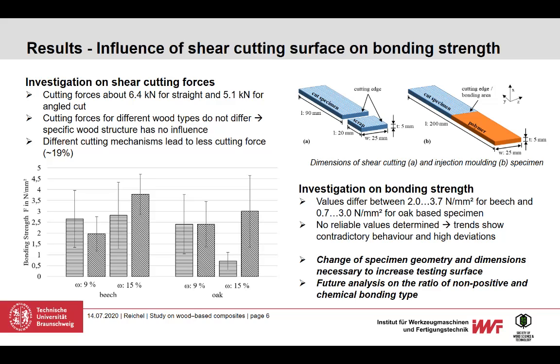We can also see that the values did not show a high reliability. So we had high deviations between single parameters and no significant trends could be shown. What we plan to do is optimize the testing specimen. So the relations we want to change in future experiments are creating a higher surface area on which the bond can be tested.